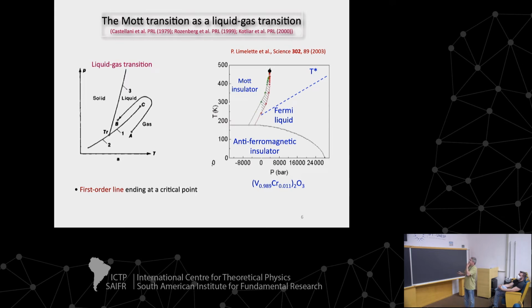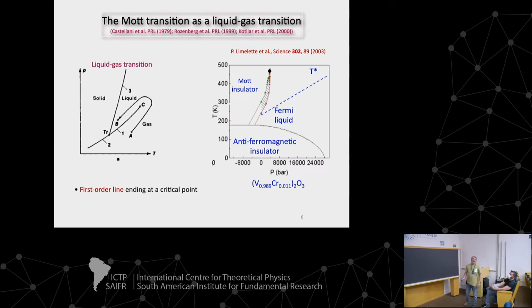Now, there is a very strong similarity between this phase diagram and the liquid-gas transition. Okay, so the liquid-gas transition, generically, is also a first-order transition that ends at a critical point. And you can actually go continuously from the gas to the liquid if you go above that critical point. And you can avoid going directly through the phase transition. So here, it's the same thing. Okay, you can go from the Fermi liquid metal to the Mott insulator if you go around the critical point.